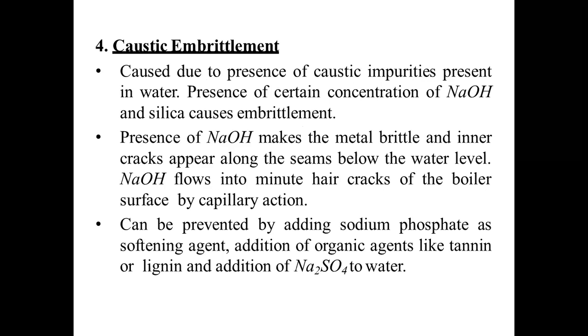The fourth effect is caustic embrittlement, caused due to the presence of caustic impurities in the water. The presence of a certain concentration of NaOH and silica causes embrittlement. The presence of NaOH makes the metal brittle and inner cracks appear along the seam below the water level.